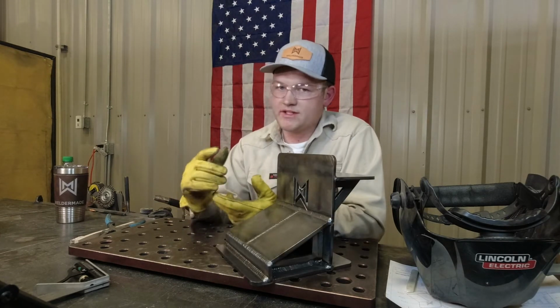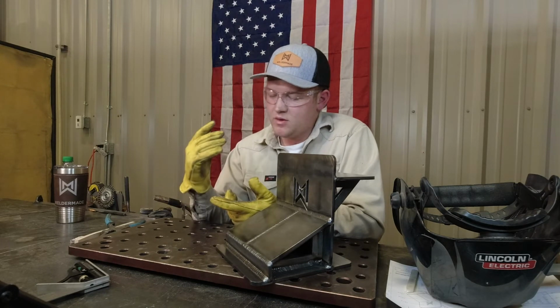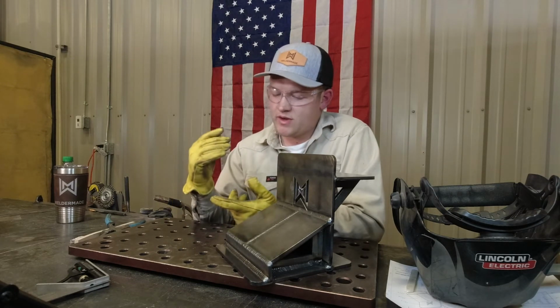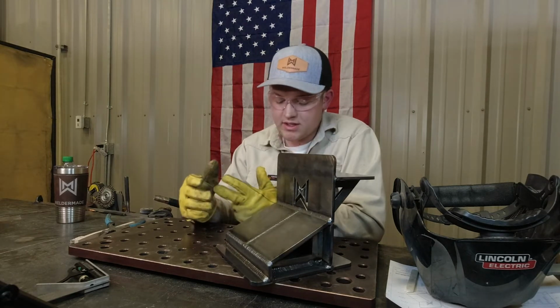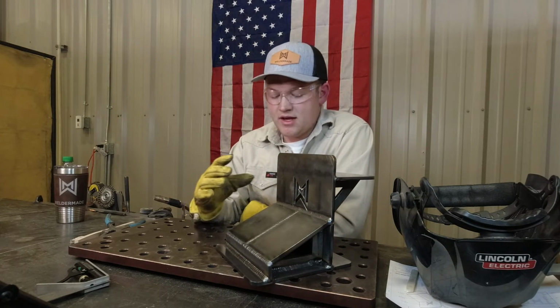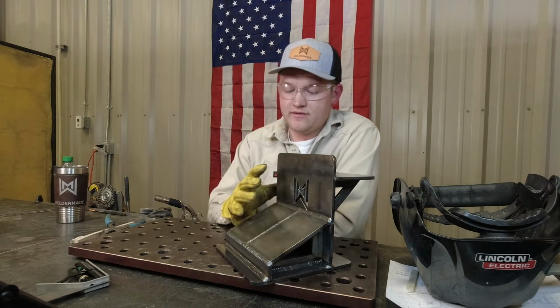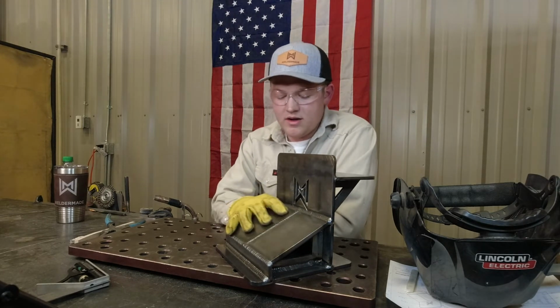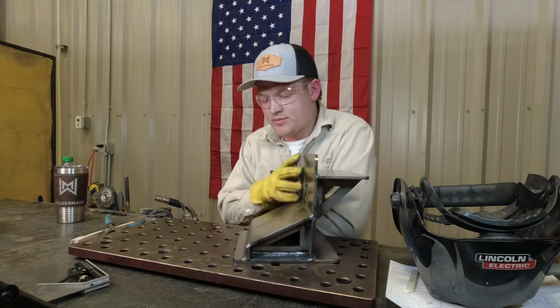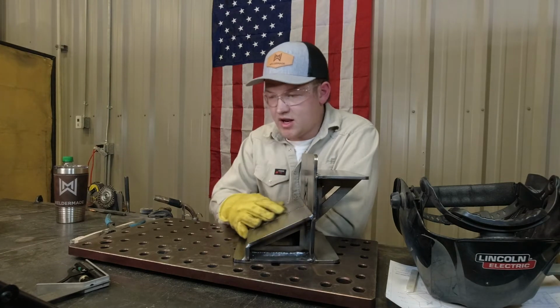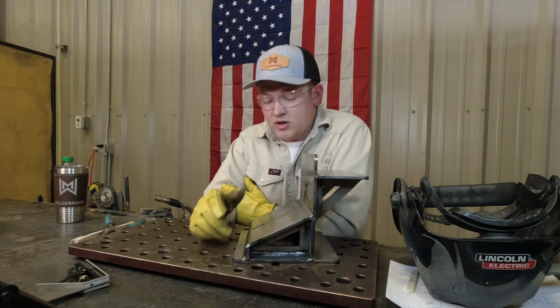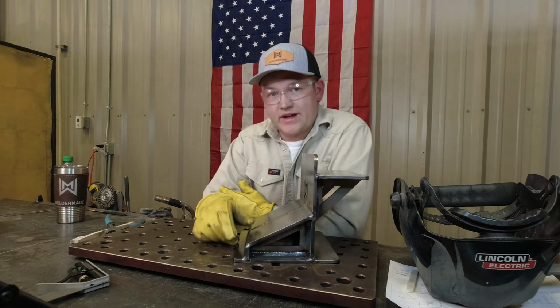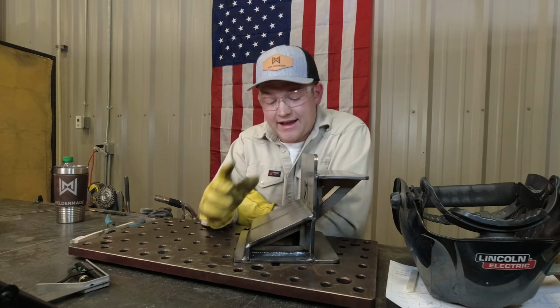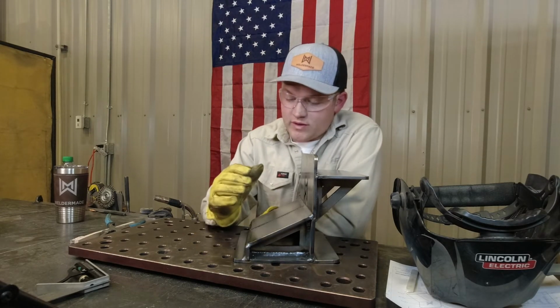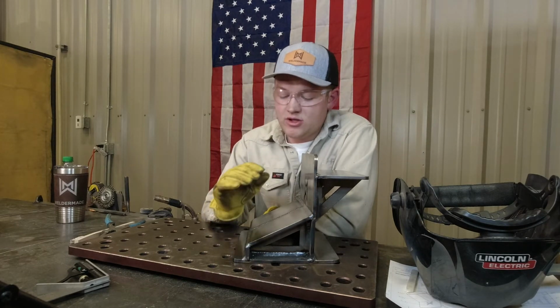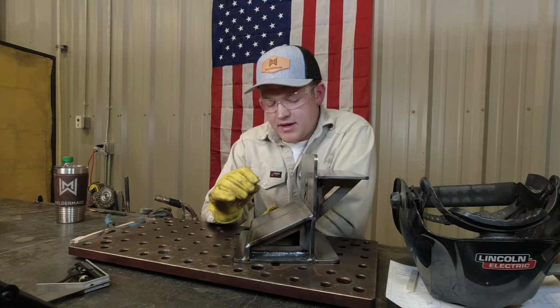We're going to go over all the steps of what we did today. We evaluated the blueprint. We made sure we had all the parts. We cleaned the parts properly. We laid them all out correctly, and we focused on getting nice and even fit up, nice and square. And then we focused on getting proper weld size. We focused on not getting any weld discontinuities or any weld defects like porosity or undercut or lack of fusion or anything like that. So focus on making a nice, clean, straight, smooth weld, and make